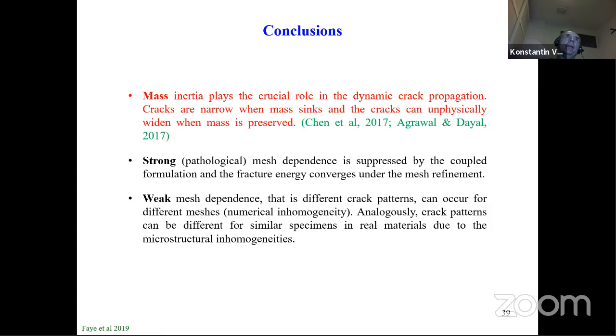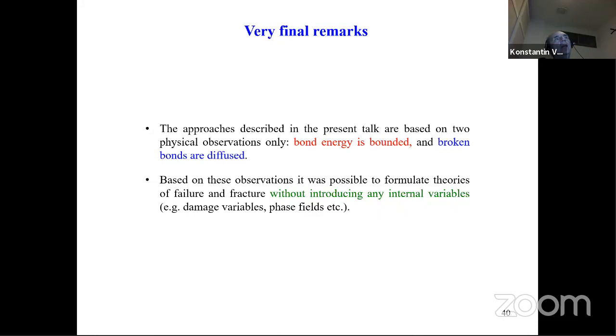Very final remarks. The approaches presented are based on two physical observations: first, bond energy is bounded; second, broken bonds are diffused. Based on these observations, it was possible to formulate theories of failure and fracture without introducing any internal variables — no damage variables, no phase fields. It's purely physically based. Thank you.